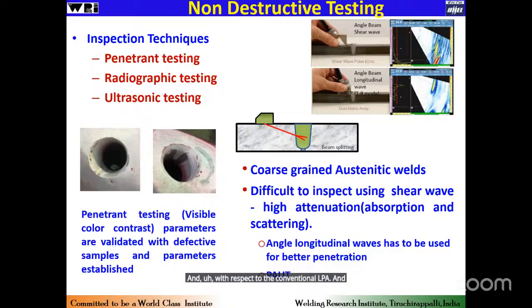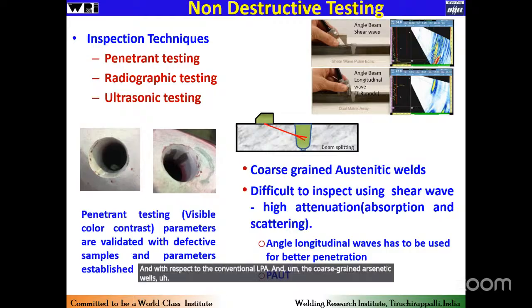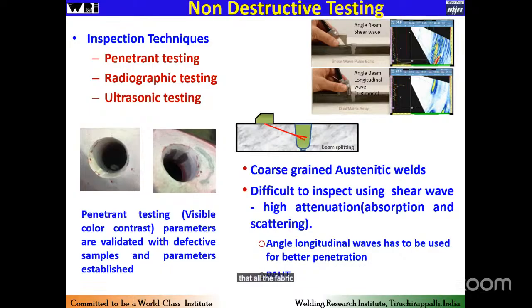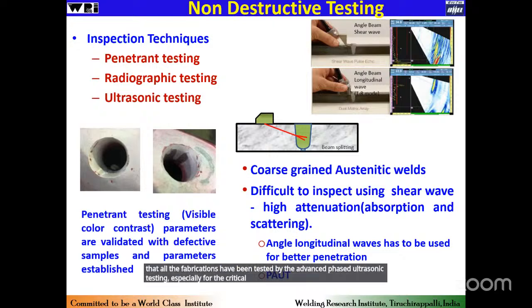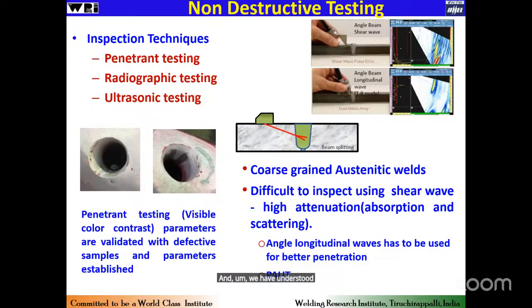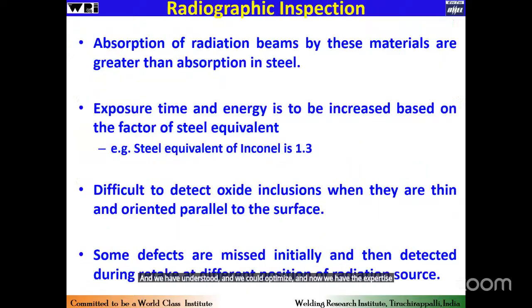And for coarse grained austenitic welds, we cannot use a conventional shear wave. Because of its high attenuation, especially because of absorption and scattering, we have to go for angle based longitudinal waves, and that has been done. And of course the use of phased array ultrasonic testing has also been successfully established, ensuring that all the fabrications are tested by advanced phased array ultrasonic testing, especially for critical applications. We have understood and optimized, and now we have the expertise to do the inspection as well.